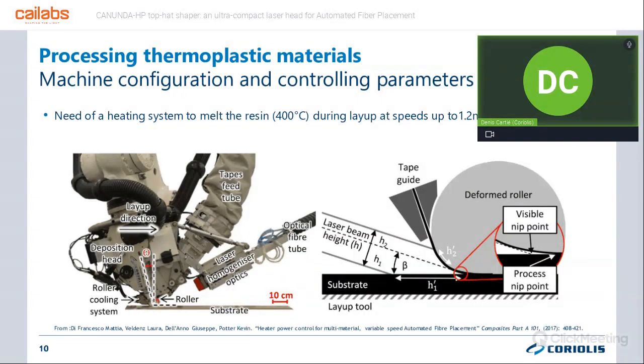So now a bit more in detail into processing thermoplastic materials in the technology using the automated fiber placement machines. As I mentioned before, to manufacture parts, the head is going to roll onto the surface of a tool. On the one hand, we have tapes which are fed into a tube into the deposition head. On the roller here, which is at the base of the head, which is rolling on the surface and applying pressure on the surface. For people who know composite materials, thermoplastics are solid at room temperature. So in order to make the plies stick on top of each other, you will need to heat the material and reach the melting point of the resin so that the two plies are welded together.